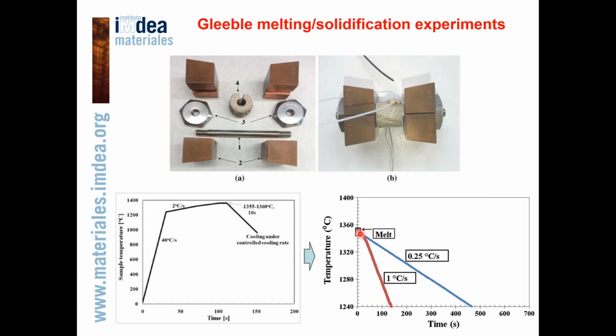cooling rates. And on this temperature-time plot, two curves are shown from solidification experiments with cooling rates of 0.25 degrees per second and 1 degree per second.